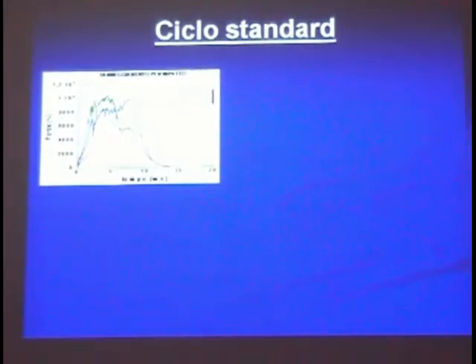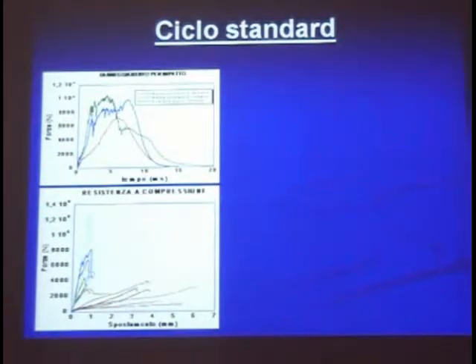This is a typical series of curves obtained from the impact, from the striker at varying impact energy. The red is at low energy. You see there is a rebound which is almost perfectly elastic, no damage, but as you increase the energy, some damage is apparent on the curves. And it has a strong effect on the force displacement curve in compression.